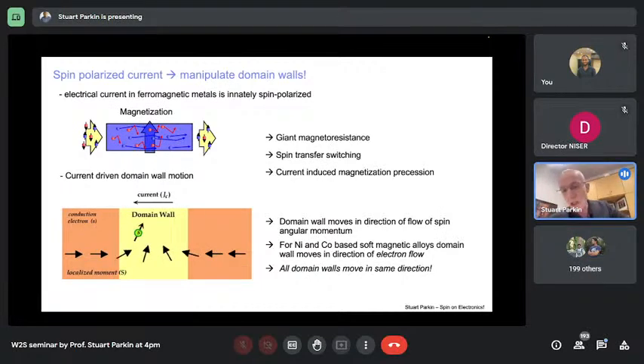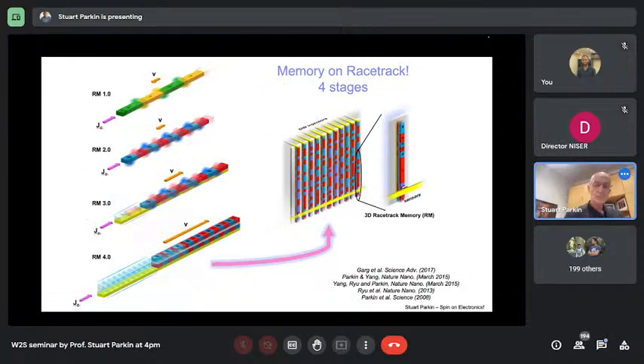And that's what we showed initially in some very soft nickel and cobalt-based materials, in which we knew from the decades of work prior to this that nickel and cobalt-based magnetic alloys can have very large polarization of the currents, up to 70%, passing through those alloys. This is why originally I decided to look at these materials.